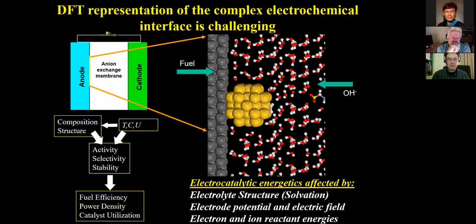And this is challenging in electrocatalysis. It's challenging because it's hard to make a model atomistically of what an electrocatalytic interface looks like. So this is a cartoon. This is not a result or something I can run with a DFT calculation. But this is meant to show you that our catalyst is most often a metal particle sitting on a carbon high surface area, less expensive support. That's then in contact with an electrolyte. Here drawn is a water solution, which is often what we'll be using in a lab experiment as an electrolyte.